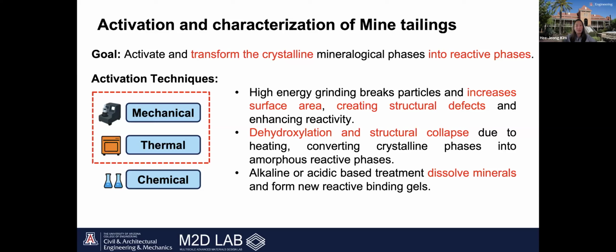And there are three main activation methods. The first one is mechanical activation, which breaks particles, increases surface area, and creates structural defects that make the material more reactive. The second one is thermal activation, which uses heat to change stable crystalline phases into amorphous ones. Under the right conditions, it can also form new and highly reactive phases. And the last one is chemical activation, which uses alkaline or acidic solutions to dissolve minerals and create new reactive binding gels. In our research, we mainly focused on using mechanical and thermal activation methods to study how tailings can become more reactive in cementitious systems.